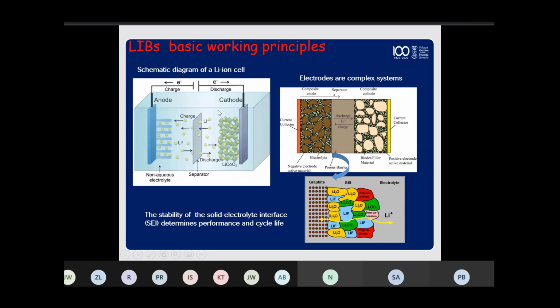Lithium-ion cells are complex systems. Apart from the active materials, you have a liquid electrolyte, generally non-aqueous, so generally organic solvents, in which a lithium salt is dissolved. This increases the amount of lithium within the system. And you also have a separator, which is ionic conductive, so it's porous, so that the lithium can shuffle in and out. But of course, it is electrically insulating, to avoid short circuits, so contact between the anode and the cathode. So this is the basic principle.